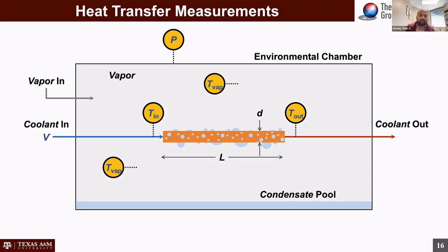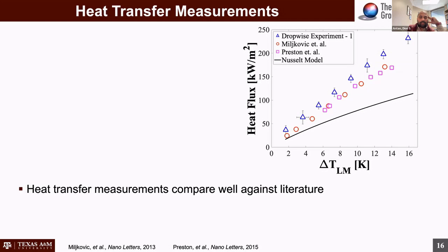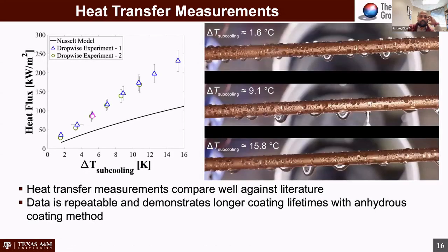We also did some heat transfer measurements, again in the same chamber, but this time we coated some copper tubes. And to validate our test setup and our measurements, we compared it to the literature. We get similar or slightly better results than what's existing in literature. And these are fairly well-cited papers. And so we said, okay, the experiments are good. In terms of dropwise condensation, let's look at what our heat flux behavior is like.